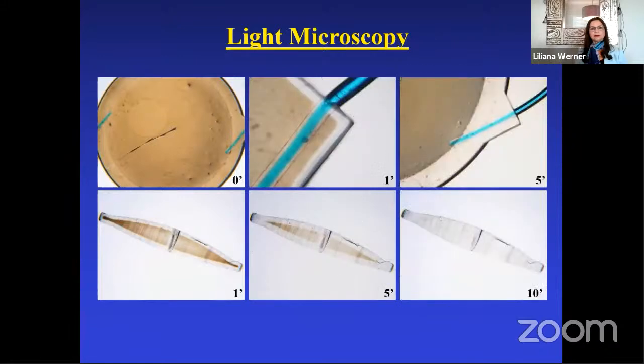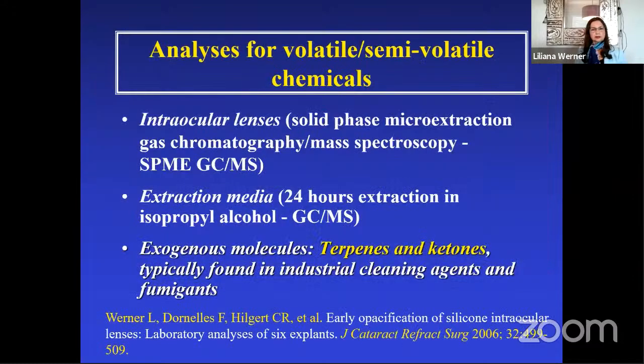The same phenomenon could be observed during examination under light microscopy. The yellow-brownish areas in the optic represented areas of opacification, and as the lenses were drying, the opacification disappeared. In this study, we had to do different analyses, including gas chromatography with mass spectroscopy, to verify if the lenses had absorbed exogenous substances. It turned out that they had absorbed molecules that are typically found in industrial cleaning agents and fumigants, such as terpenes and ketones.